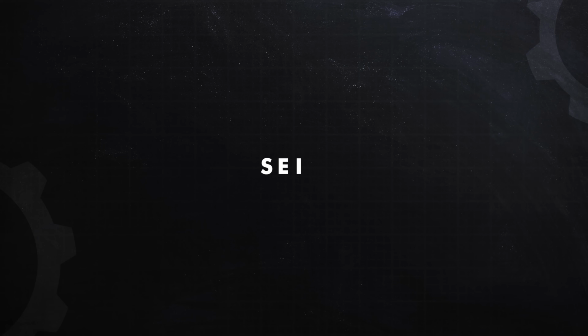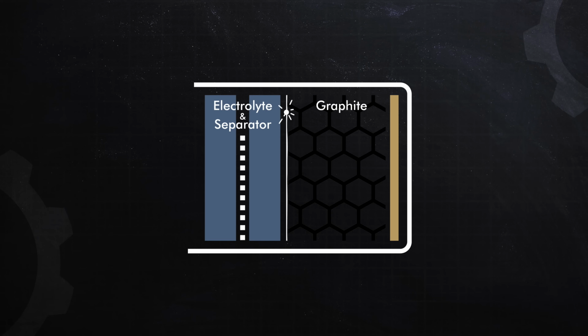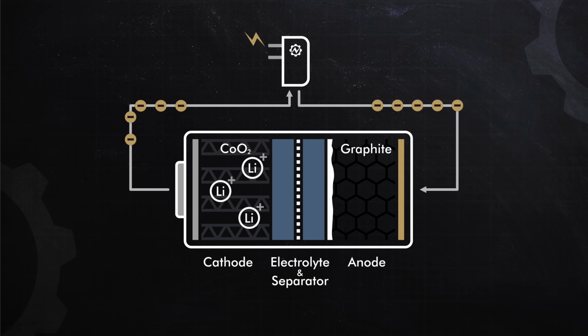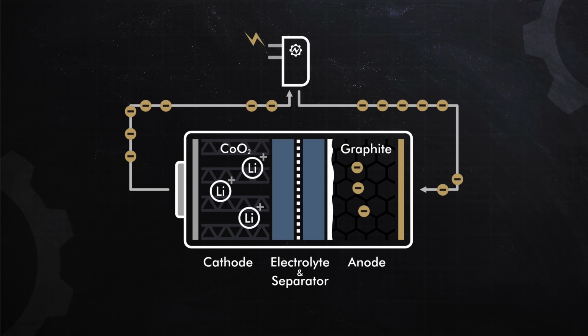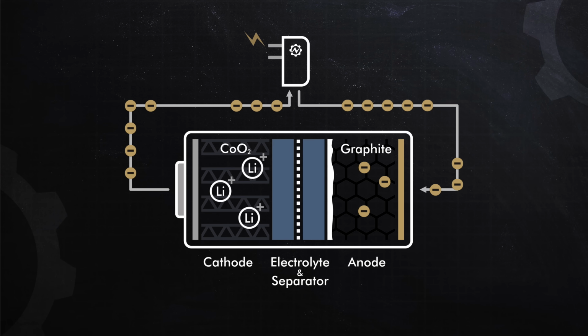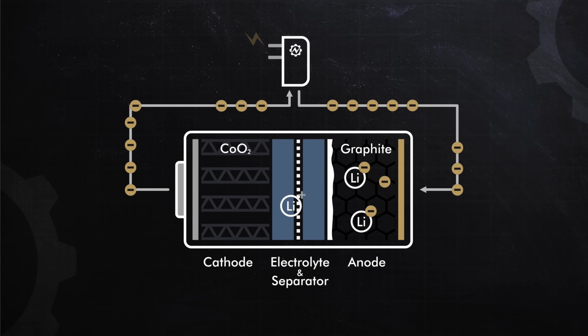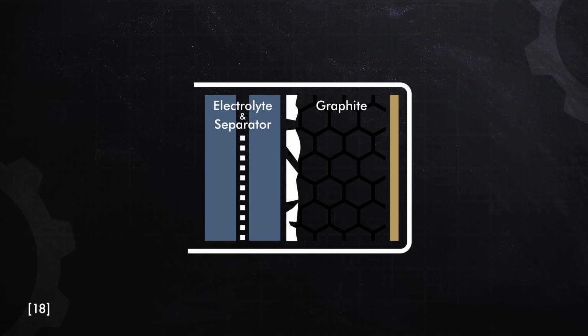The first calendar aging mechanism is the formation of inert layers on the surface of the anode. The most important of these layers is called the solid electrolyte interface, or the SEI. This layer is formed by reactions between the electrolyte and the anode, and it grows the most during the first few cycles. Forming the SEI layer does consume lithium, but it's actually beneficial, and manufacturers want it to happen. See, the SEI layer is electrically isolating, and it helps prevent electrons in the anode from tunneling across the separator and the electrolyte to the cathode. Although the SEI layer blocks electrons, lithium ions can still pass through it, and this allows the battery to function normally. Ideally, once the anode surface is entirely covered by the SEI layer, it stops growing. However, during cycling, the SEI layer can be broken up, and this will expose fresh anode material to the electrolyte, and this allows more SEI to form, depleting lithium in the electrolyte.